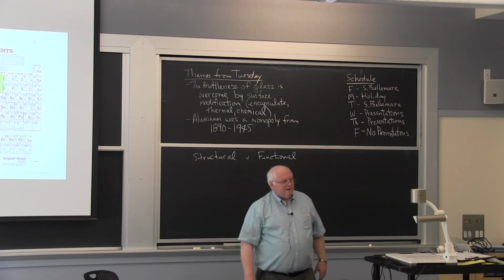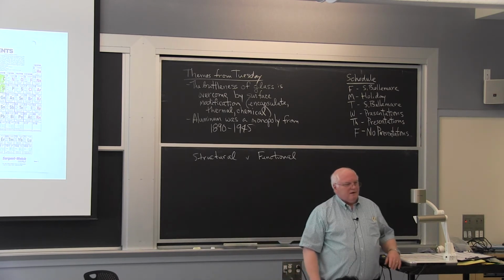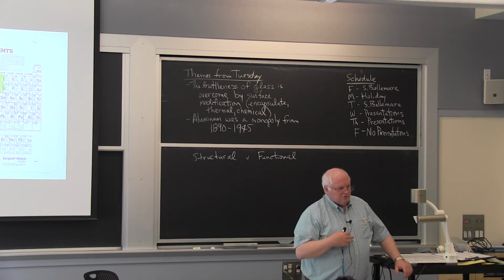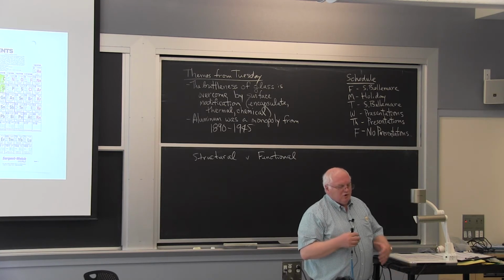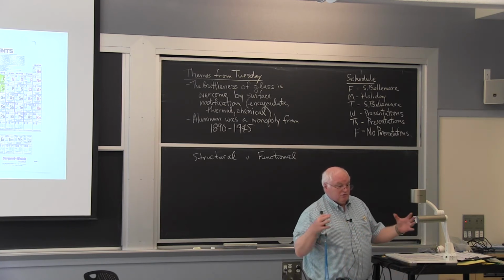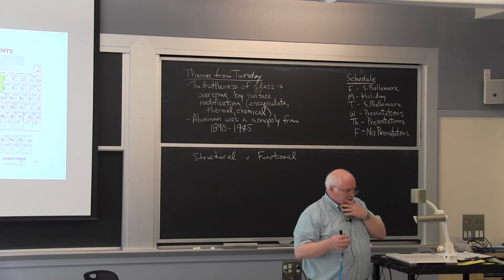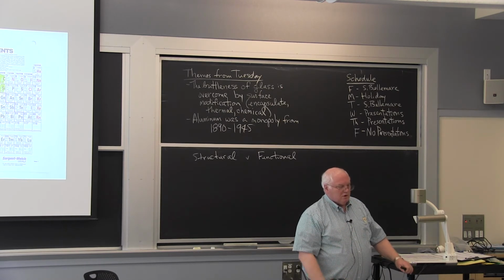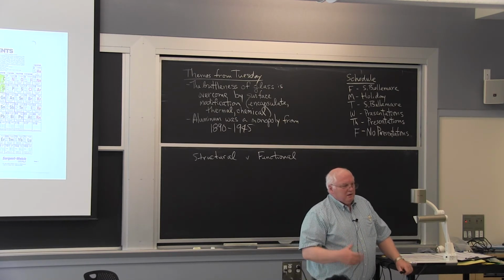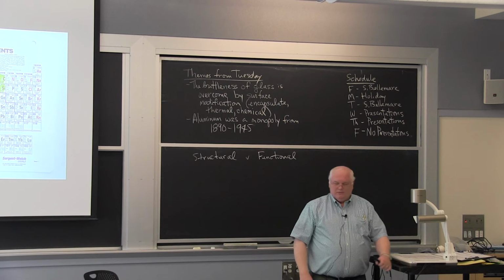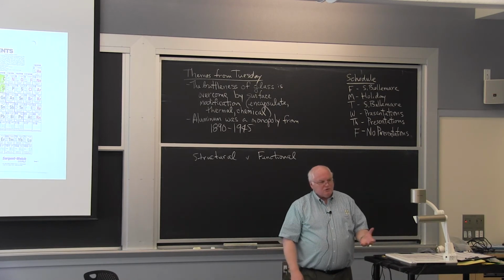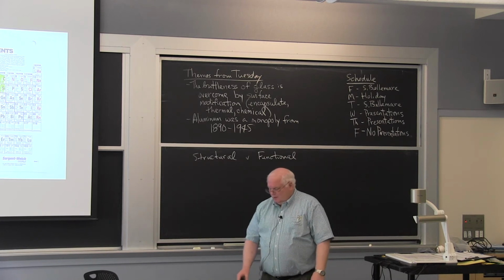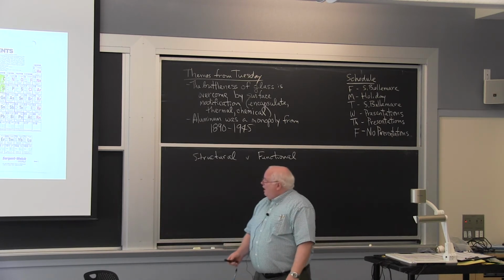Sorry, so what is the mechanism by which an impurity suppresses grain growth? It goes to the grain boundaries and it gives grain boundary drag. If you don't have impurities, the grains will grow by diffusional mechanism. If you have impurities there, you get what's called grain boundary drag. Oh, where it literally gets caught on the... Yeah, you want something that is surface active on the grain boundaries, and it gets caught, okay? It's sort of like precipitation. Precipitates will do the same thing, but even individual atoms will do it too. It's called grain boundary drag.